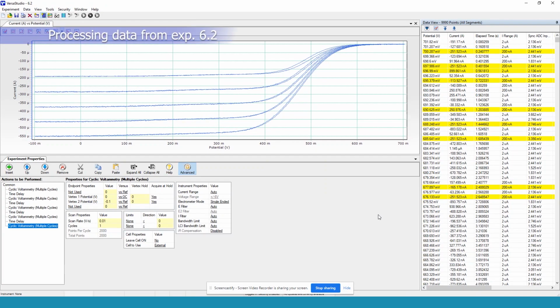This experiment shows the influence that the rotation rate has on the actual experiment. We can see that the value of the plateau really depends on the rotation rate. Basically, with increasing the rotation rate, we also increase the current of this plateau value. Now, this actually makes sense because at increased rotation rate, we end up with a diffusion layer that is much thinner. And this is because as we increase the rotation rate, we are much quicker pushing the material towards the electrode surface, and therefore we can measure more current as these active materials are being consumed in the experiment.